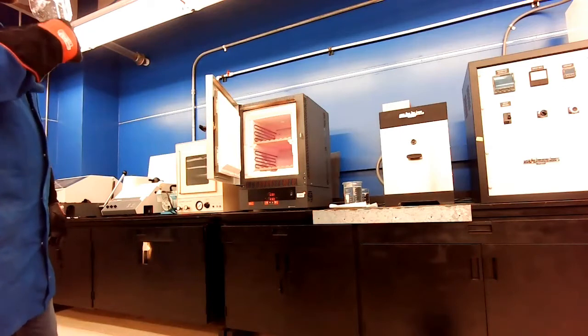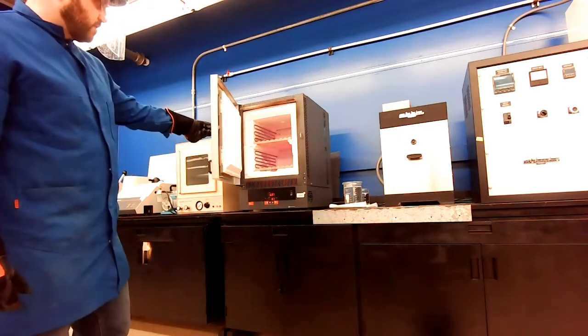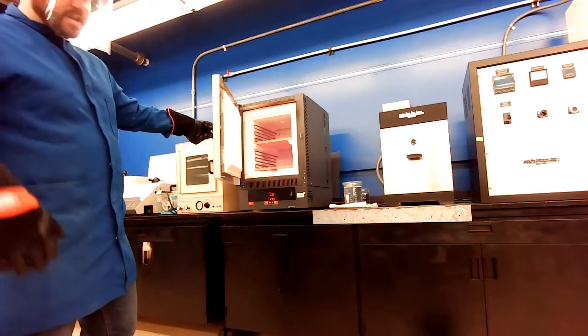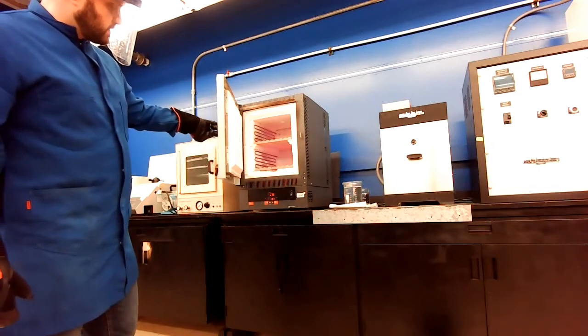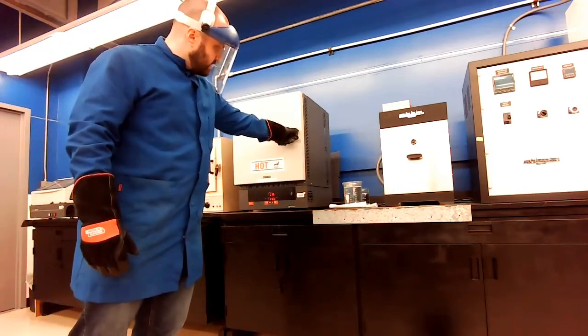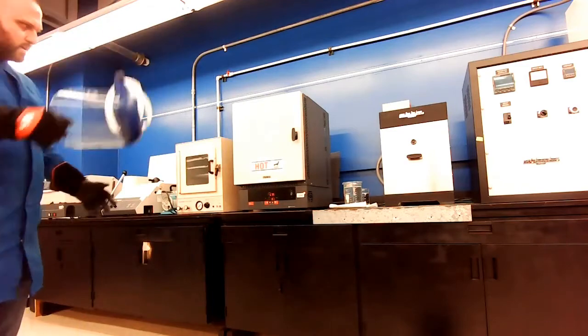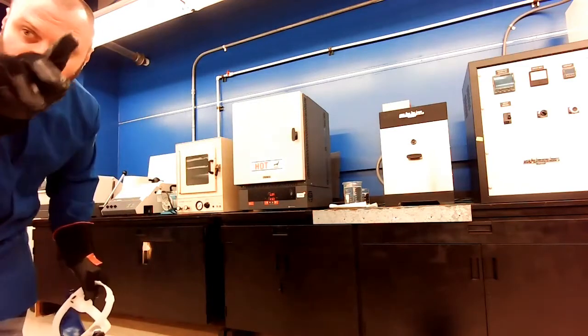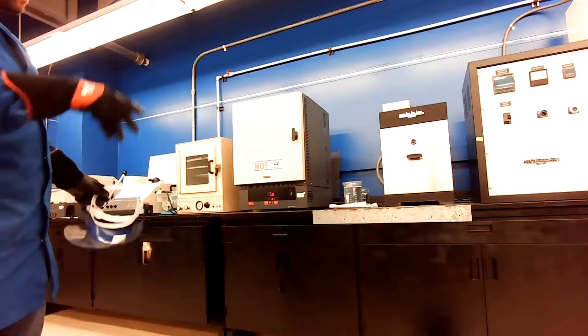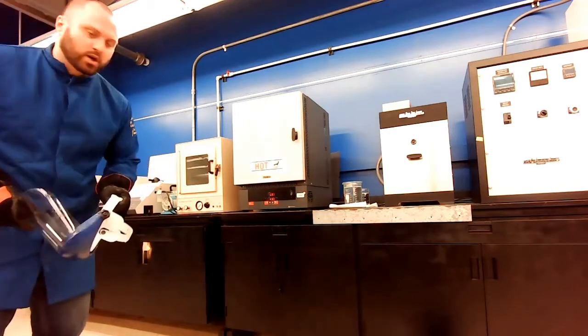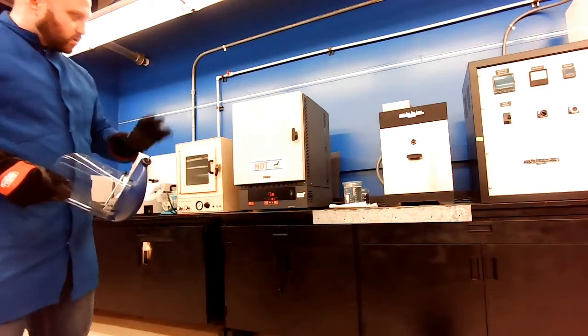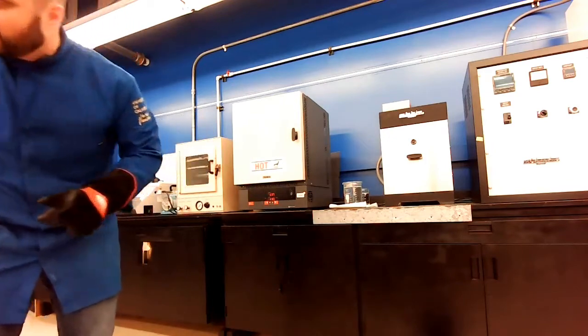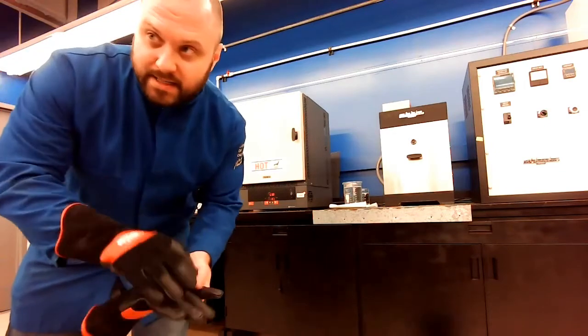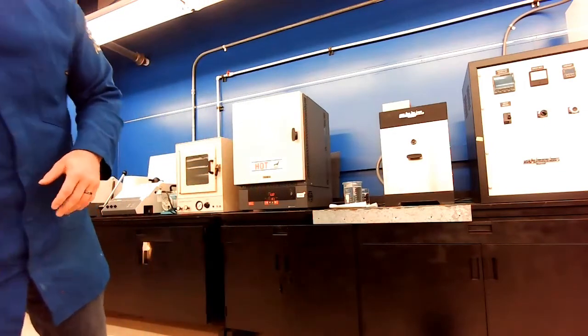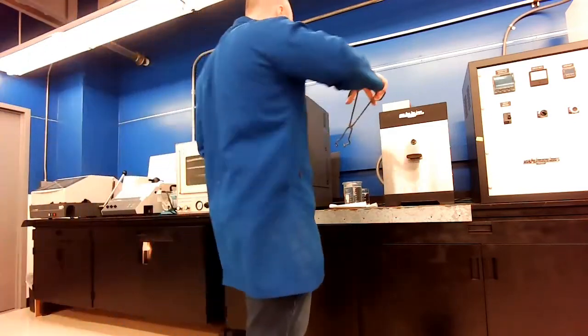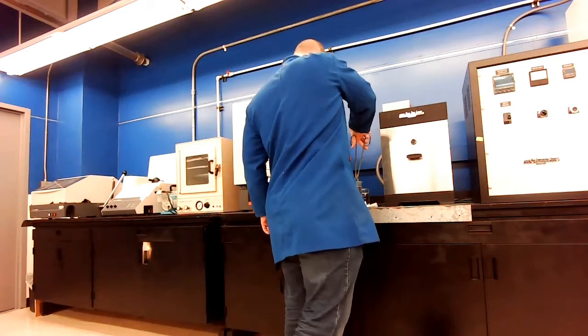My goal here is I don't want to go below 650. I want to sort of ramp down relatively fast and stay there. So 25 degrees away, I'm going to close it back up. My guess is that this temperature is going to go up a little bit. The system's fighting itself a little bit, and then it'll come back down. We'll let it sit there and equilibrate for a little bit of time, okay? So I'm not messing with the furnace anymore, so I can take off my face shield and my high temperature gloves. What I want to do, my last thing, is I want to show you these samples.